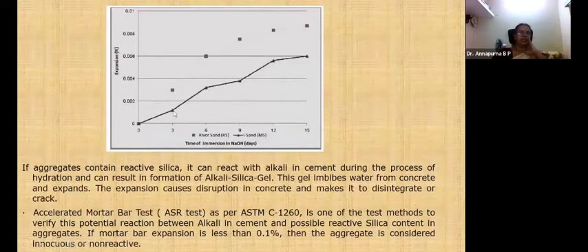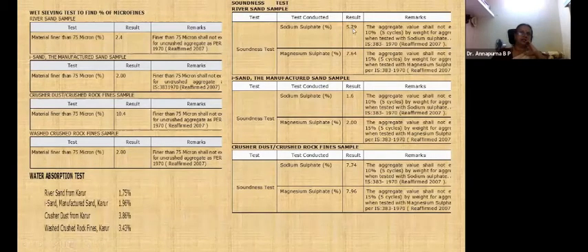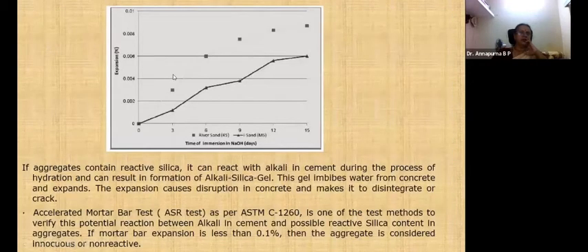Now coming over to the expansion here, this is the ASR reaction, that is, time of immersion in sodium hydroxide. When it is immersed in sodium hydroxide, this is the expansion limit of the river sand and the manufactured sand. So we saw here, due to the sodium sulfate, 5.29 and 7.64, and here it is 1.6 and 2. So on immersion in sodium hydroxide, the river sand shows a higher expansion, whereas the manufactured sand shows the least expansion.